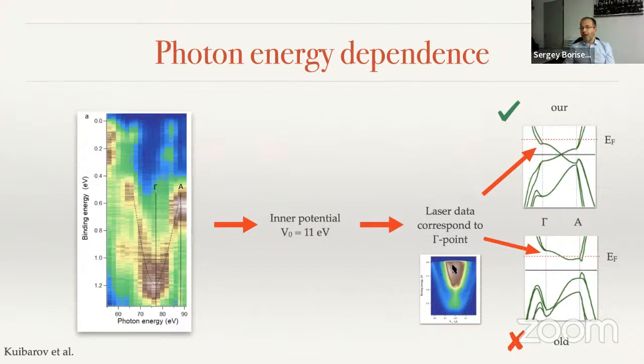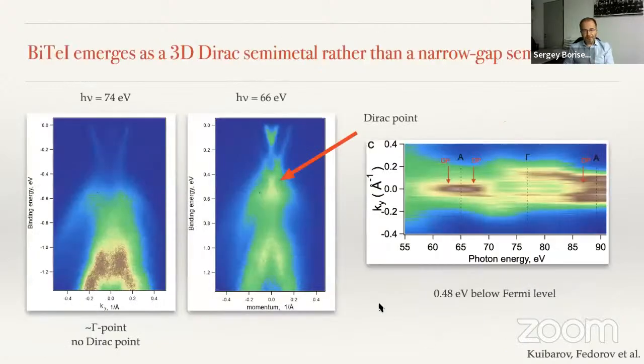Because you have the two sets which correspond to these two extremes, and these two sets of Rashba-like bands actually should appear in your spectra if you integrate more along KZ. And this is in very big disagreement with the old picture, which showed that at the gamma point there should be nothing. And there is only one set of features around the A point, and this should be smeared out by the KZ resolution.